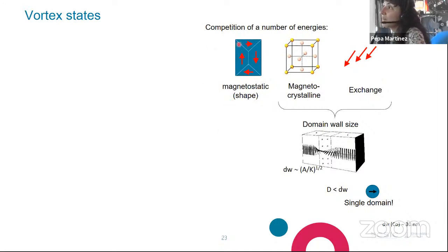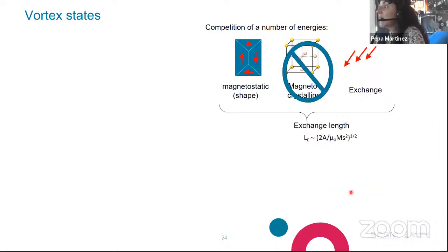And on the other hand, you have the magnetostatic or shape anisotropy. This energy tends to minimize the amount of stray field created by the magnet, okay? To reduce this shape energy, as you know, magnetic domains are formed. The size of the domain wall separating these two magnetic domains is usually given by the ratio between these two energies, the magnetocrystalline and the exchange energy. If the particles are smaller than the domain wall, particles are usually said to be single domain or almost single domain.